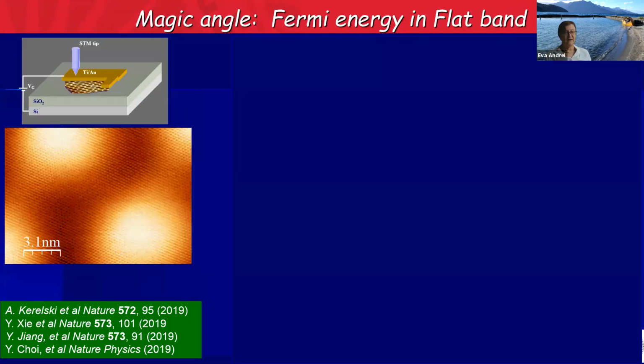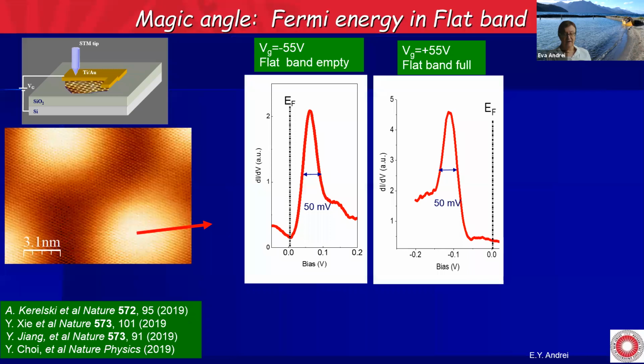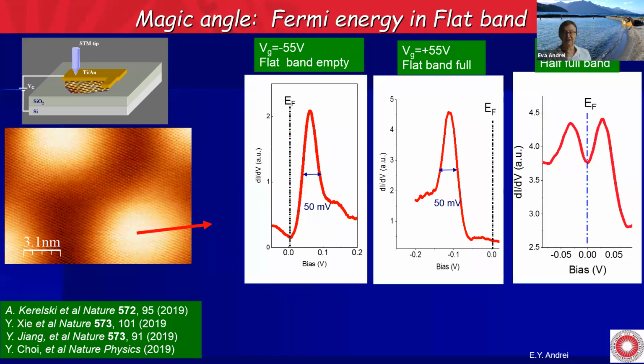And of course, the next thing you want to do is to look at the density of states, or to look at the spectra. And since we are able to gate this sample, which we were not able to do in the original experiment, we first take the Fermi energy way outside of the flat band. And you see that we have this beautiful flat band here. It's not that flat, it's about 40 to 50 millivolts in width. And then we take the Fermi energy to the other side of the flat band, and again it looks the same.